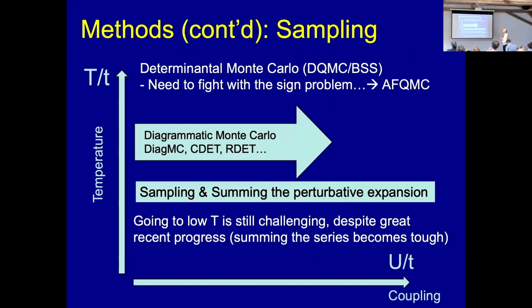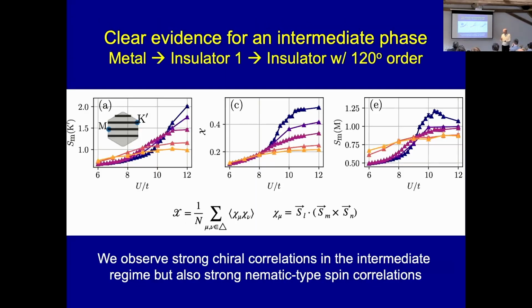And this is the result we got using the so-called minimally entangled typical thermal state method, which is a combination between sampling methods and tensor network methods. So this is the work of Alex Vitek, where we studied as a function of U this transition between the metal, the unconventional insulator, and the 120-degree insulator. And these are the various structure factors at different points in the Brillouin zone. I don't have the time, obviously, to enter into any details.